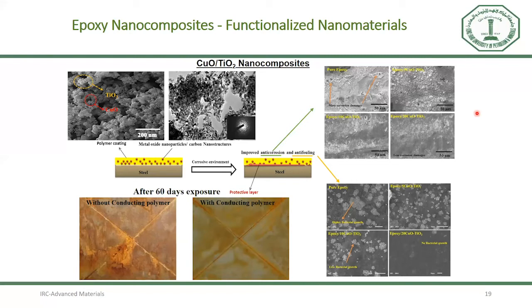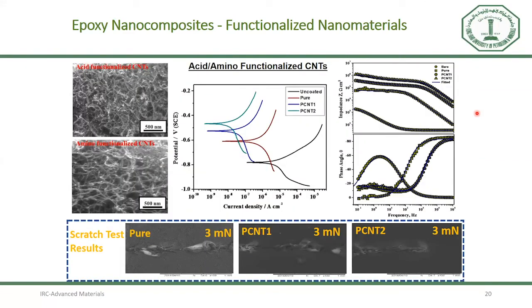Whenever we use the copper oxide and TiO2 nanocomposite, we found that the anti-corrosion and anti-fouling performance of the resultant epoxy nanocomposites is increased. Similarly, we used carbon nanotubes and dispersed them into the epoxy matrix. It is a very tough process because of the agglomeration of the CNT. To avoid the agglomeration and ensure homogeneous dispersion, we did acid functionalization and amino functionalization separately on the walls of CNT. Then we incorporated this functionalized CNT into the epoxy coatings. Interestingly, we found that amino functionalized CNT can easily improve the properties of the resultant epoxy nanocomposite coatings.